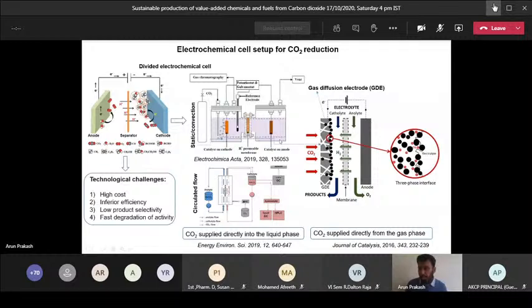Usually acetonitrile is what we use to fill the compartment of the reference electrode, so that you can use it as a non-aqueous reference electrode. And imidazolium cation containing ionic liquids. Those who are working on organic chemistry or pharmaceutical chemistry may have heard about ionic liquids. These are imidazolium ion containing compounds, and they have high conductivity. So that's the reason for using ionic liquids.